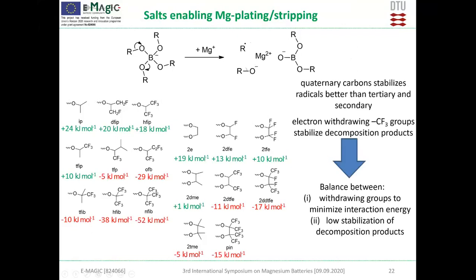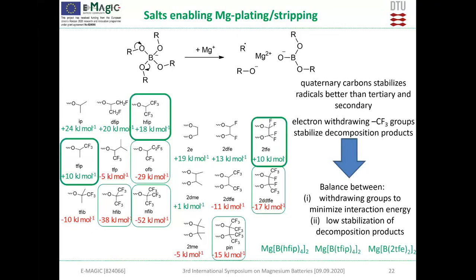break the structure. So when we design an anion, we need to find the balance between this withdrawing of the electrons, due to which we want to have low dissociation energy, and not too high withdrawing because we will lower the stability. So if we look at the structures selected on the previous slide, with the ones that the calculations show have stability, we can see these three, and indeed this is the one that is extensively studied in our project.